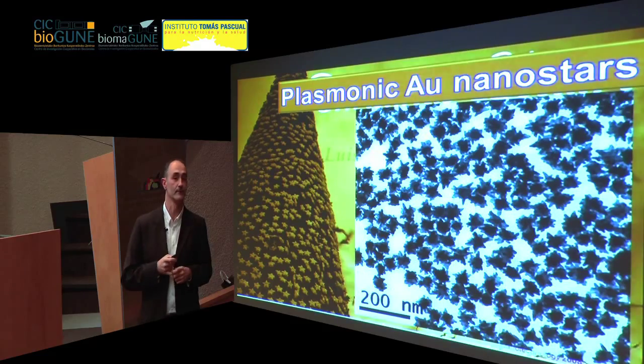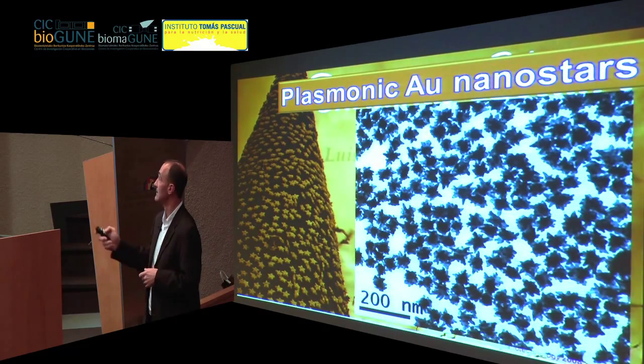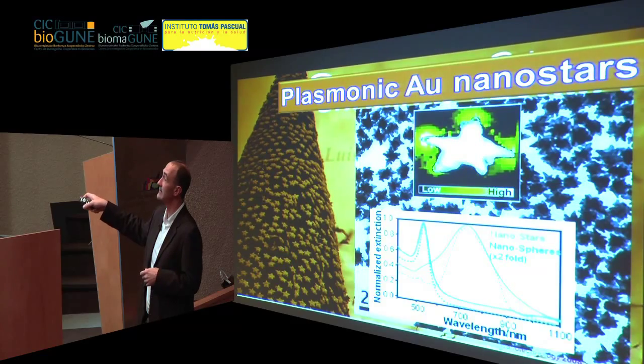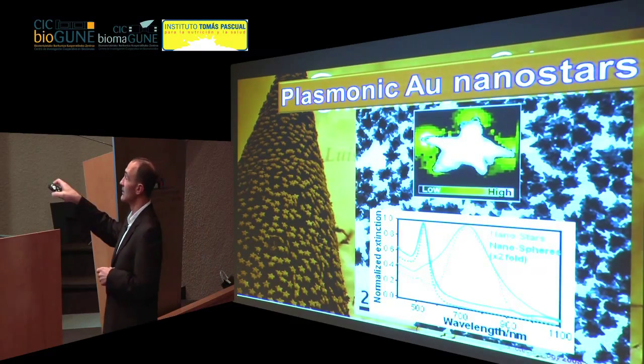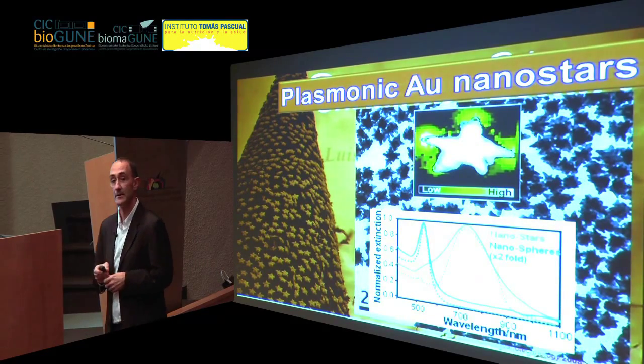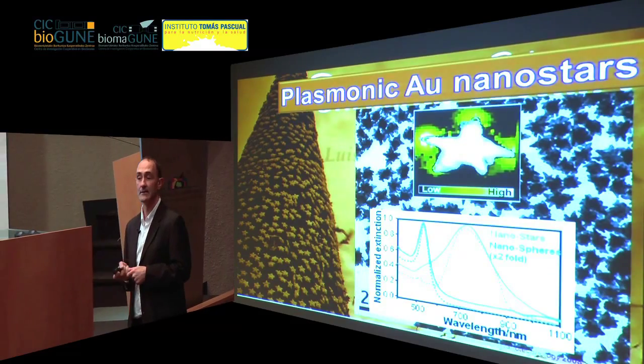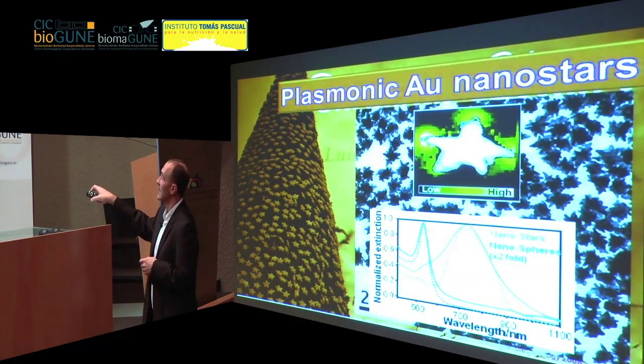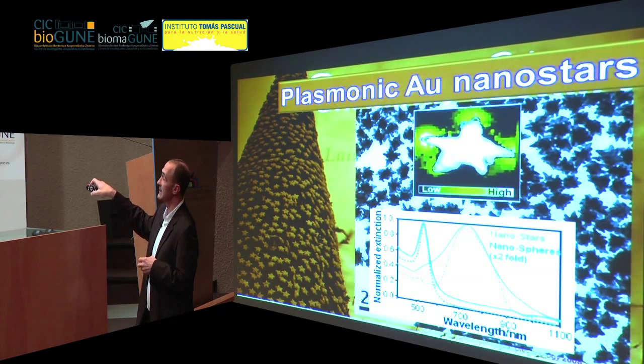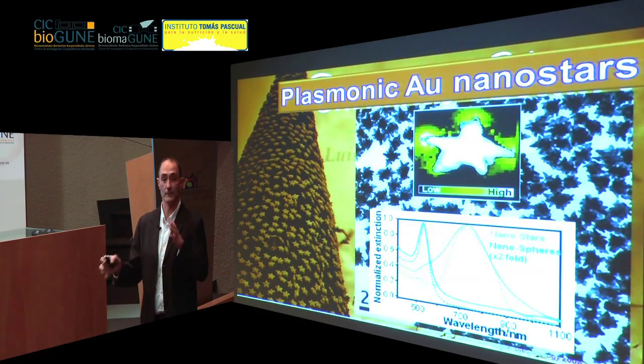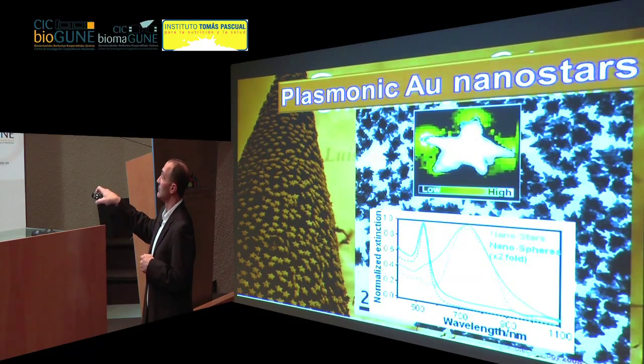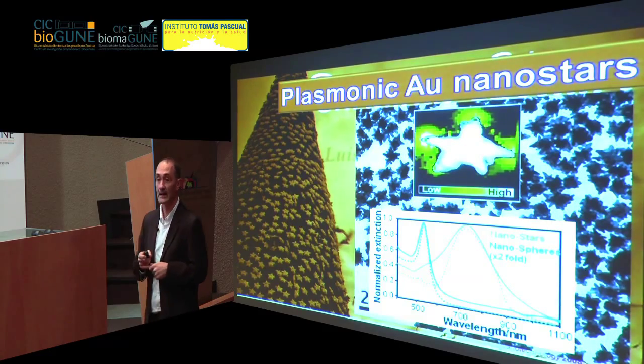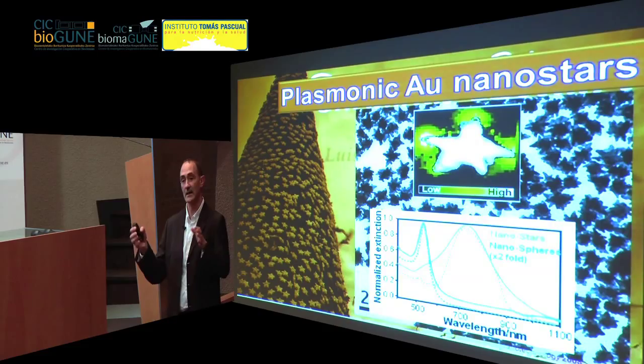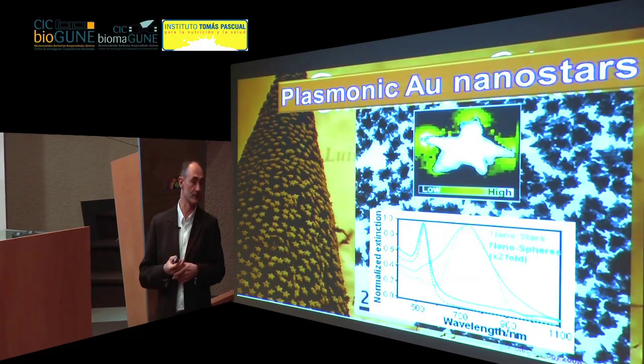Don't ask me why the particles grow like this. We don't understand this so far, but we know that they can be used for very interesting applications because they have very interesting properties. For example, we determined that when you excite the plasmon resonances in this type of particles, you can get a really high confinement of the electric field at the tip, with intensities that are much higher than those that you obtain for spheres. Additionally, the absorption spectrum of the nanostars is completely different to the one that you get for spheres. This is a comparison, again, of theory and experiment for both systems, so it makes sense. And we also know that if the field is concentrated so highly at the tips, it's much more sensitive to what happens in the neighborhood of the surface than for spherical particles.